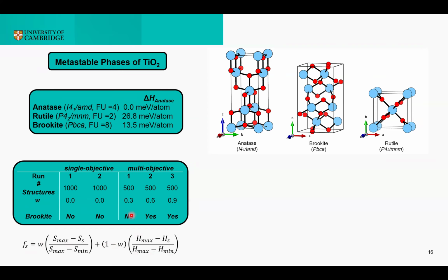the advantage given by the similarity index doesn't seem to kick in, while if the weight is more or less 0.6 or 0.9, and the weight goes from 0 to 1, so that the search is almost completely driven by the similarity index, then we really see that we can find the brookite quite easily.